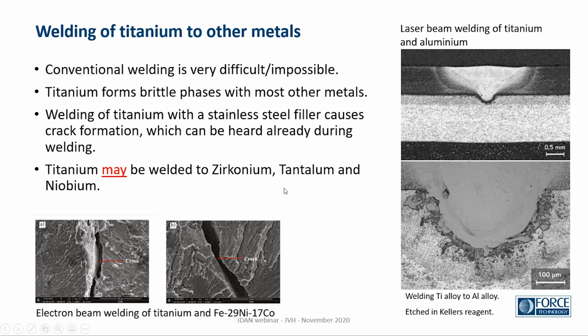That could be zirconium, tantalum, or niobium. And we do see that some problems with dissimilar welds including titanium are controlled by using tantalum as a buffer layer, but it's very rare to see it. Some examples of welding titanium to an iron nickel cobalt alloy. You can see the cracks have formed due to the brittleness.